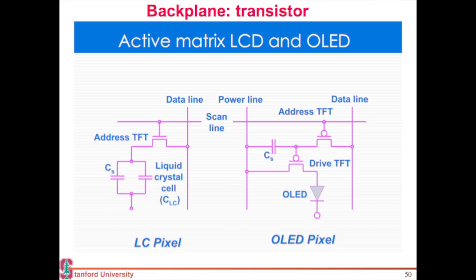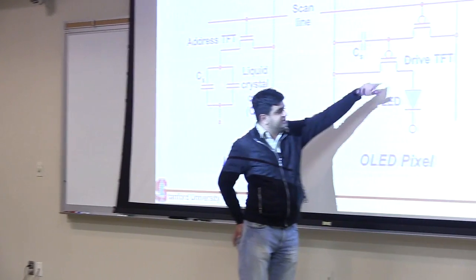These amorphous silicon or these amorphous zinc oxide transistors, they always have variability in current when you operate at low current regime. There are effects known as RTN or other variability effects. So for organic LEDs, the only option available is this low temperature polysilicon. I talked that LCD, all you need to do is apply a voltage. In an OLED, you actually need to drive this diode. So you need to supply it with current.